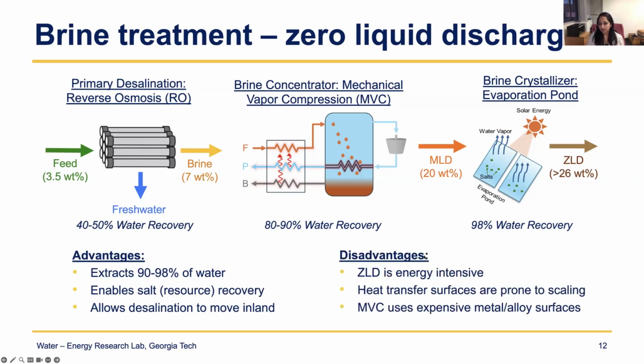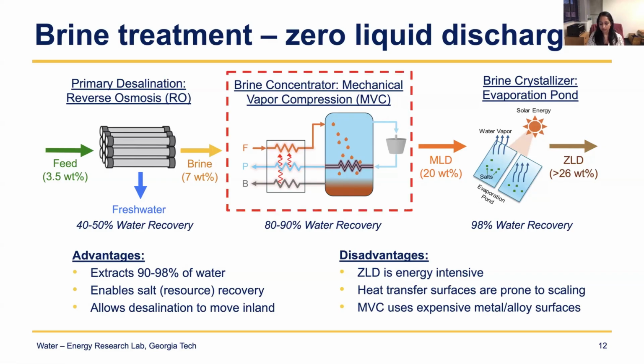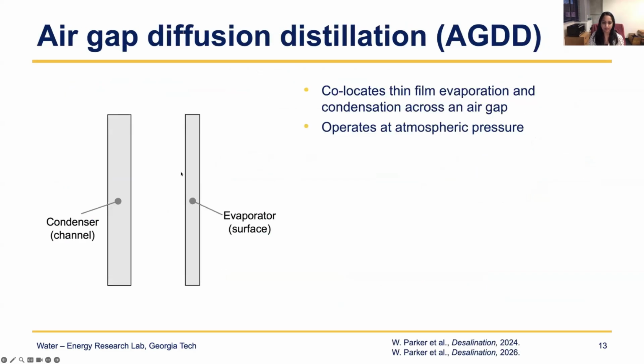The disadvantage is this process is very energy intensive, and mostly it uses heat exchangers here, as well as for the evaporation ponds. And the heat exchangers corrode under these very high salt concentrations. So you have to use very specialty alloys in order to make it function. So we are really focusing on how you can do this brine concentration as well as crystallization in a much more efficient and lower cost manner.